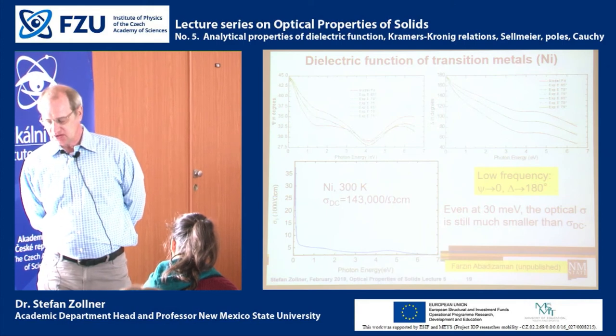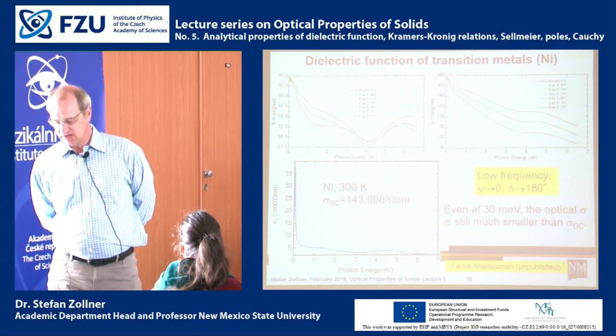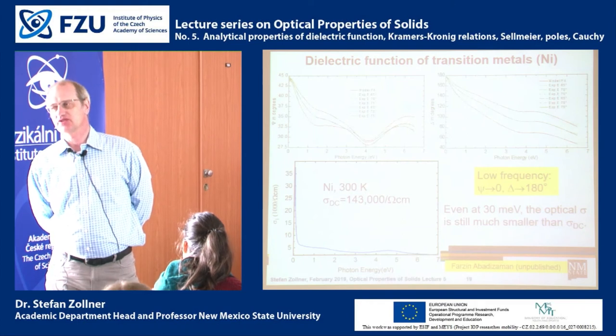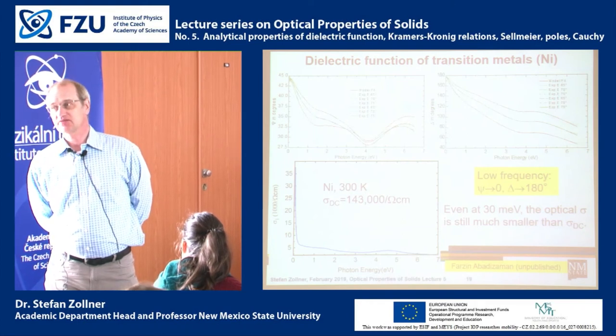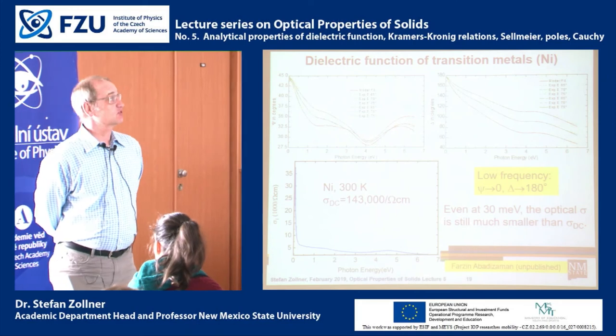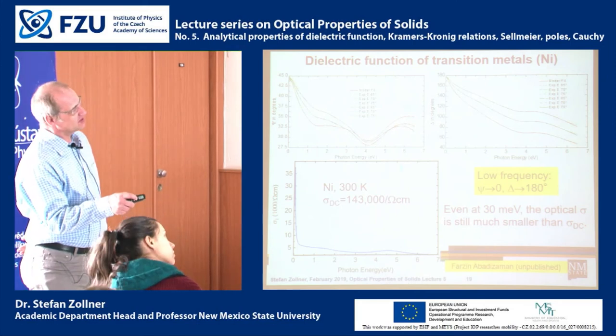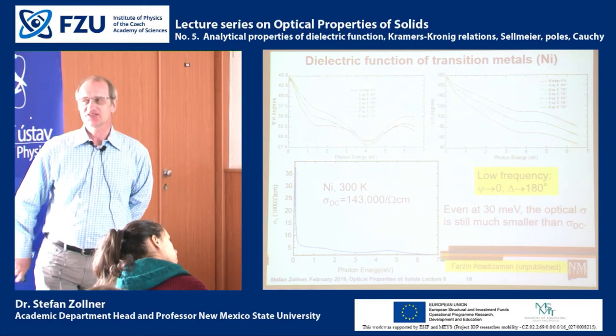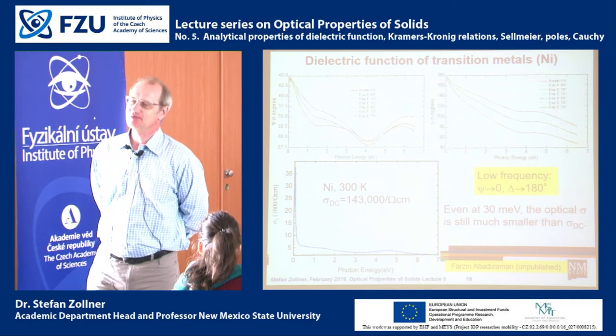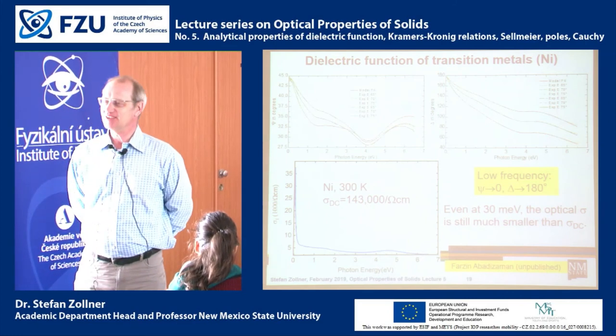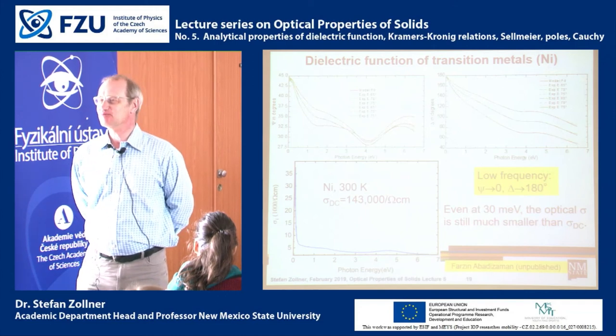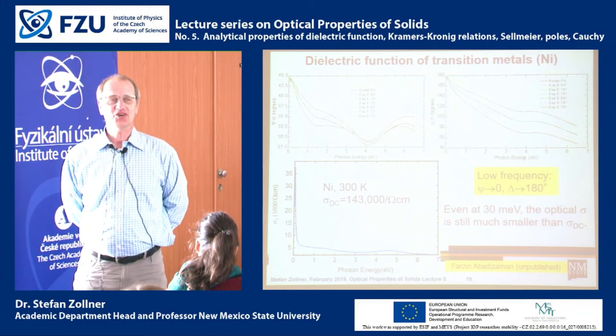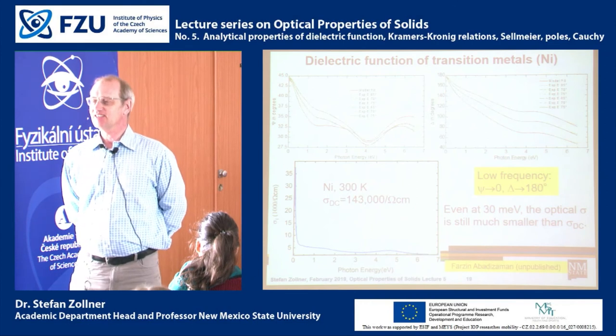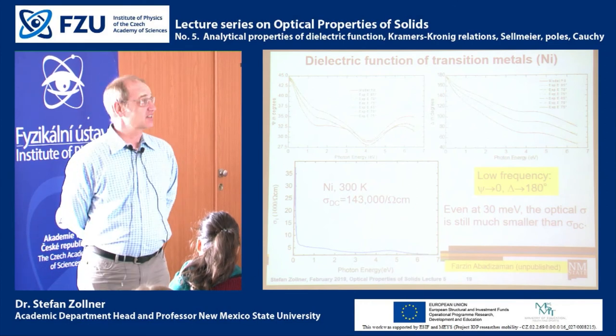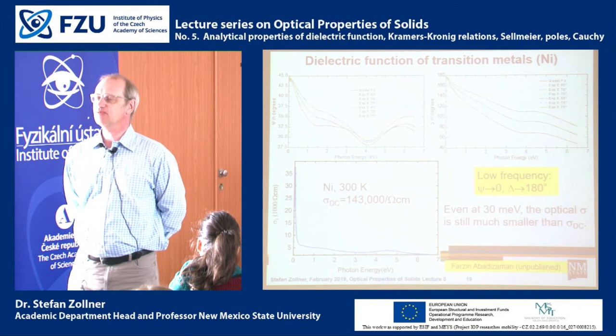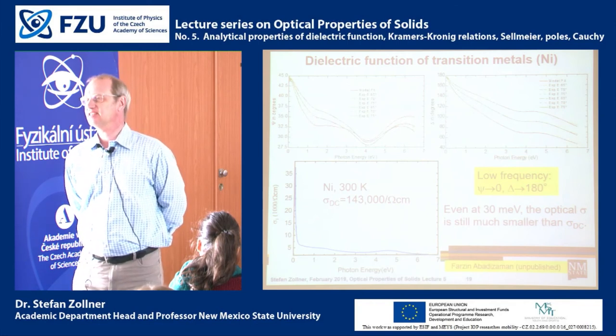So part of your question has to do with the abruptness of the surface, right? And like I told you, we've been cleaning nickel for 5 years, and every student is trying to clean it better than the previous one. It is very difficult to get this nickel clean, and the best way that we found was that we heat it overnight at a high temperature.